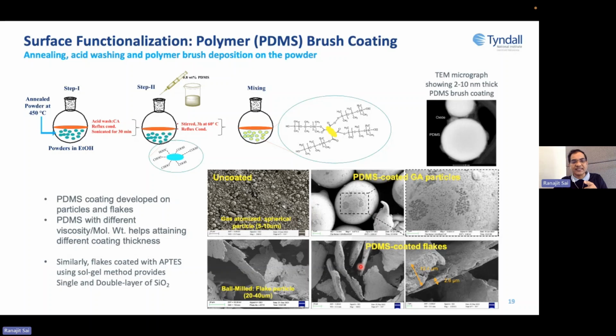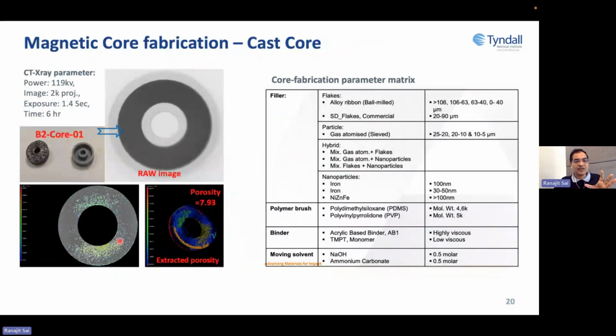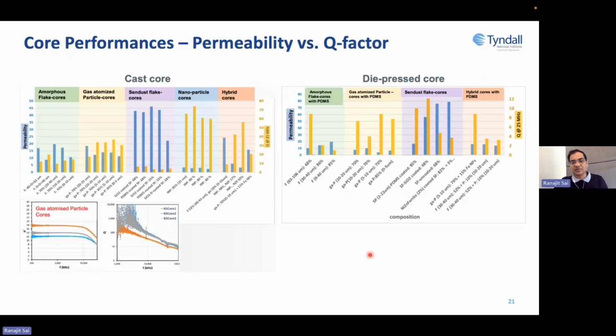Then after getting those things, we make some test cores. And you see that during the making of the test core, we have to be very careful about the pressure we are using, because the porosity matters, and porosity will change your material's property and the core's behavior eventually. So there are so many different parameters to play with, like different fillers, polymer brush behavior, different binder, and different solvent, and so on. So it's like a multi-parameter optimization process. And through this optimization process, you will get different kinds of inductors.